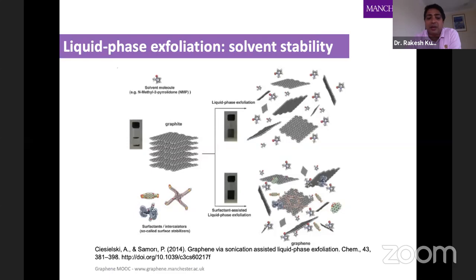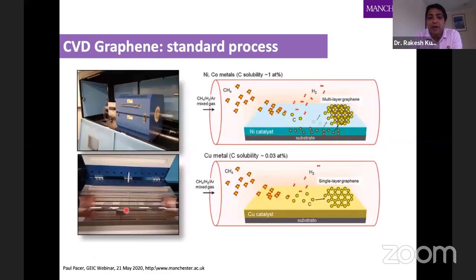surfactants and intercalators, because these surfactants actually intercalate between the layers and then separate out during the sonication process. The other method which we were talking about is CVD-based graphene. So with CVD-based graphene, you can actually make a large-scale graphene on a metal surface, and generally they use nickel or copper as a substrate for growing multi-layer graphene or single-layer graphene.